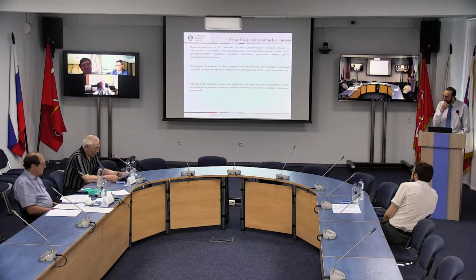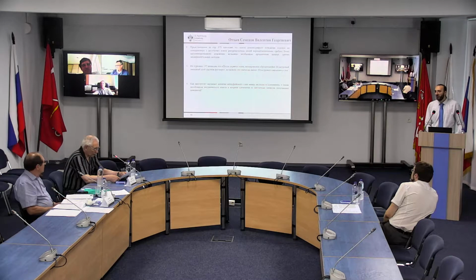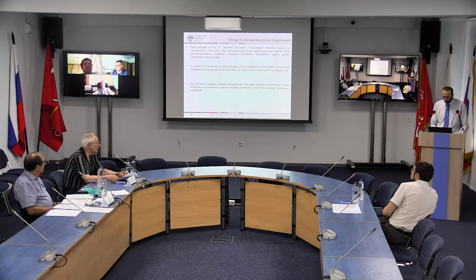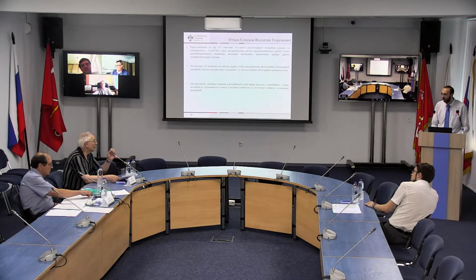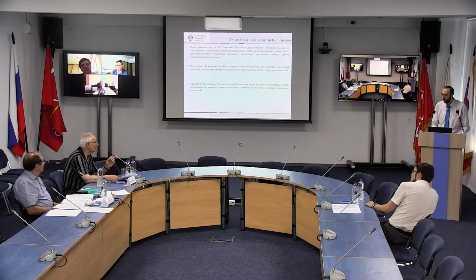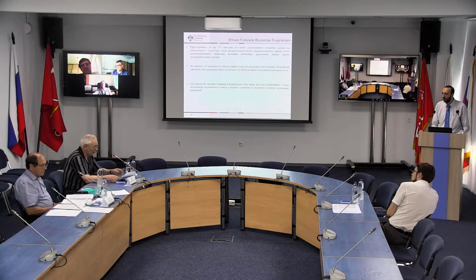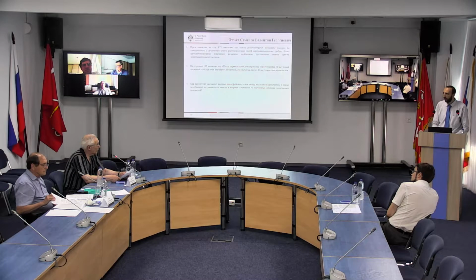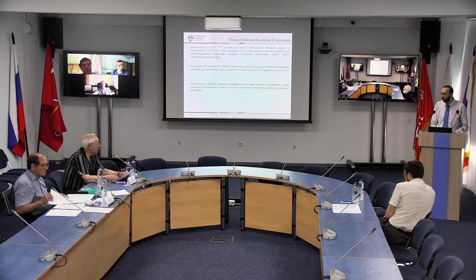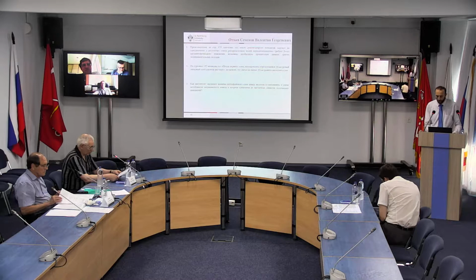And how do you assess the influence of the interface layer between ferromagnet and aluminum and this unavoidable roughness in the channels of the aluminium matrix, and what's the impact on magnetic characteristics? And it was mentioned that when you have an aluminum matrix or silicon matrix, on the border we have an interface area of oxide, for example, compounds with silicon or with aluminum. So how do you think, can this interface layer influence? Does it exist or not?